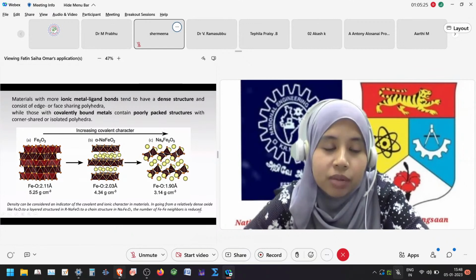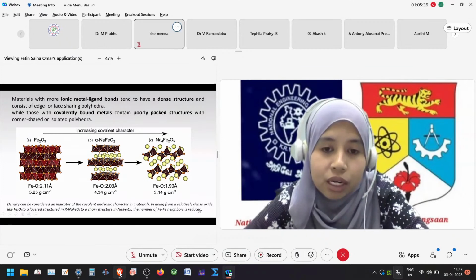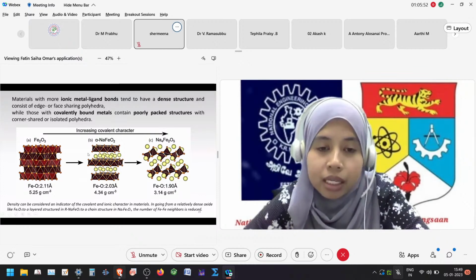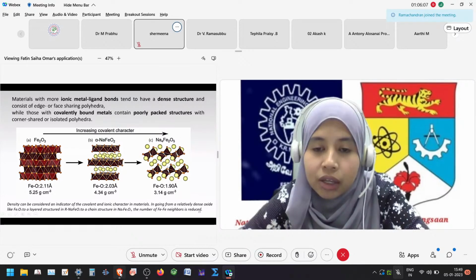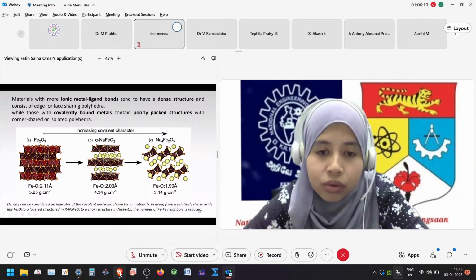Actually, the dense structure of the material is not very good for energy storage because there is no space for the diffusion of the electrolyte ions. But if the structure has a gap between the layers, it means that they will allow the electrolyte ions to pass through them. So there's a gap, and this is the electrolyte ions. The electrolyte ion is able to go through the crystal structure of the materials. And this is the open-pack structure, another form of structure. There's a huge gap between the crystal lattice, so the electrolyte ions are able to pass through and interact throughout the structure of the electrode material. The larger the gap between the crystal, the more space for the electrolyte ions to pass through.